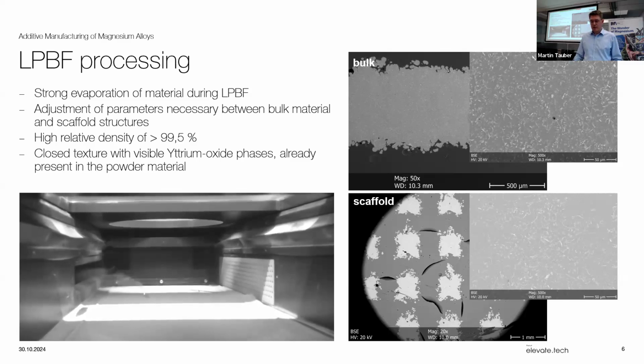And for both, we can really form fully dense materials, as you can see in the cross sections in the bigger magnification. And what you also see in the bigger magnification, there's some lighter parts, which is the outer surface of the powder particles, which is the oxide, and you can find this within the final part. And for this case, it was WE43, the alloy that we used, which is a rare earth-based alloy with yttrium phases in it.